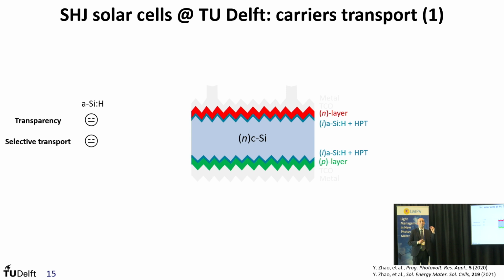Then, as I said, the next point is to decorate this passivation layer, that has to be thin enough to let the charge carriers go across, with the doped layers. So I already mentioned that amorphous silicon-based doped layers are not really interesting. They are absorptive. They are also not that conductive because the doping activation in those types of amorphous layers is not that good.